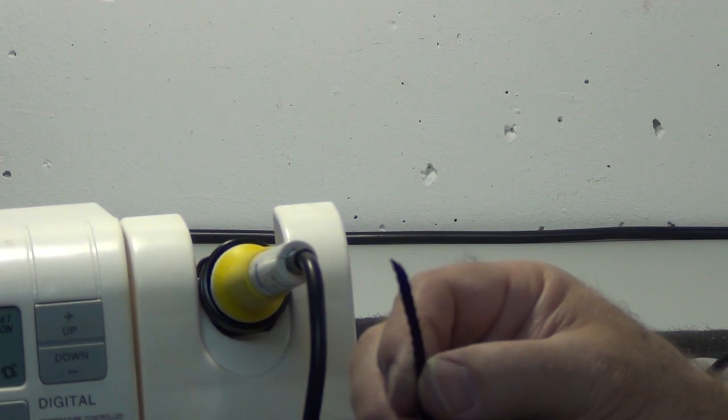So I think you'll agree there is a way to get this to melt at a rather nice temperature. And it didn't happen immediately. It took a little bit of time, which showed for me that we're close to the melting point and not vaporizing it immediately. I'm sure I could reduce this, maybe to 250 and see if it still melts. But certainly it didn't at 200, which surprised me. So here we're zooming out again now.